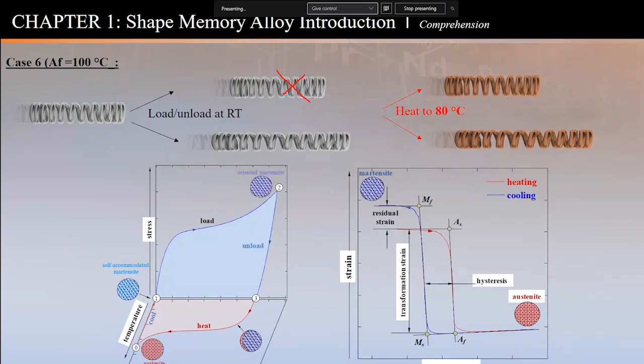Top option, okay. Any other guesses? I guess the only other guess will be the bottom. So if you said the top option, if I heat to 80 degrees C, it's going to shrink back to what it was before. And the answer is no. And here's why. Remember, I mentioned that I bought this material, or I made this, its AF is 100 degrees C. Here's that AF, right? You can see it here. I'm only heating to 80 degrees C. So 80 degrees C is still over here. As I heat here, I didn't do anything.